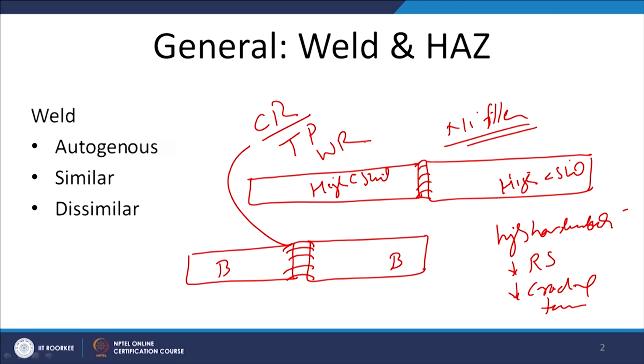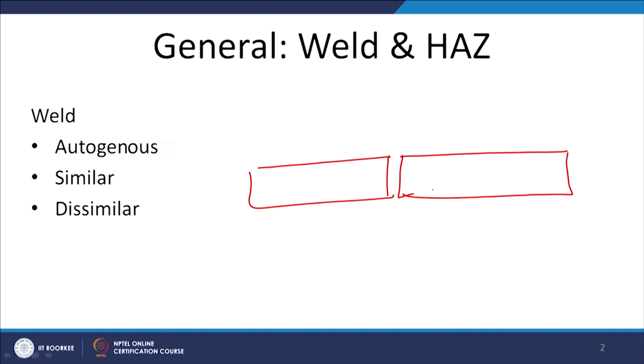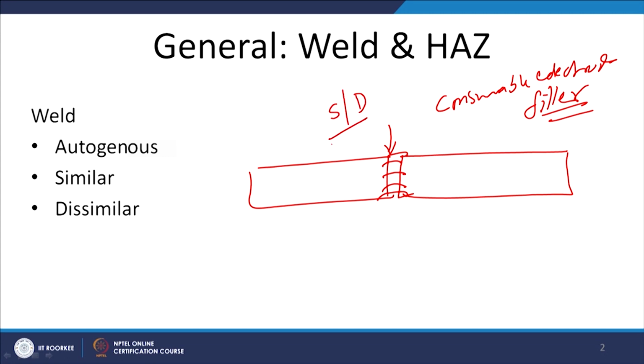So, we can choose the filler or the electrode composition suitably, so that it has the required set of properties for the weld metal. So, if we consider this aspect, at least we have the flexibility in the case of fusion welding processes, where either a consumable electrode is used or the filler is used from outside. We have the flexibility to select the suitable filler, so that the weld metal composition can be regulated accordingly in order to have the required microstructure, mechanical properties, corrosion resistance, wear resistance.